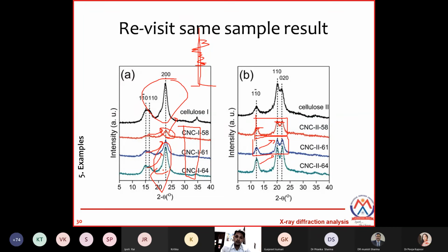at this place. One more thing I want to tell you, as you are moving towards the y-axis, the interplanar distance is increasing. So if some peak is at 40 degrees and some peak is at 10 degrees, it means the 10 degree peak has a rather larger distance than the 40 degree peak. So we call it left shift and right shift. If there is a left shift, it means the interplanar distance is increasing. If there is a right shift, then it means interplanar distances are decreasing.